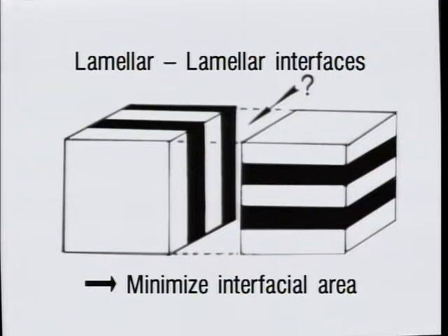What we see here in this sketch is a grain boundary formation. We're looking at a supposed polymer blend, let's say 50-50, which would naturally form lamellar sheets, where the interface is a minimal surface, a very simple one, planes. However, there's no reason for these planes to be oriented in a particular fashion. For example, on the left they might start out to be vertical plane interfaces, whereas on the right they might start out to be horizontal plane interfaces.